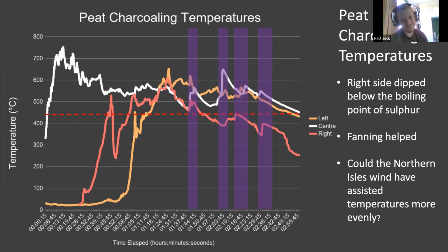The natural draft would have quite likely assisted the charcoaler in maintaining temperatures above this sulfur threshold. In addition, of course, to just being more experienced, I doubt this sulfur problem that we had would have been an issue for somebody in the past, in the region that we're looking at.